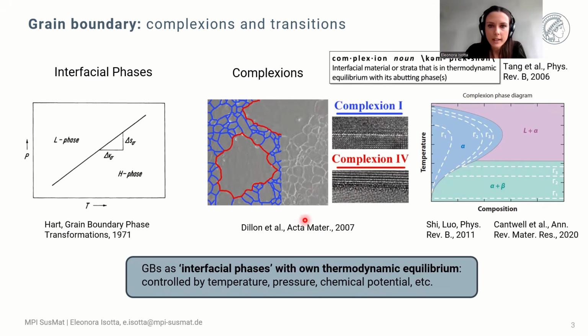For example, in one case study, complexions were studied in alumina, and different types of complexions were identified, recognized as one of the causes of the abnormal grain growth in the material. The idea is that the presence of some type of complexions was leading to this grain growth because their structure and chemistry promoted faster mobility of the boundary, causing abnormal grain growth. The key idea is that being able to control the boundary phase via thermodynamics leads the way to the development of phase diagrams, where based on thermodynamic conditions we could predict the specific grain boundary phase that forms.